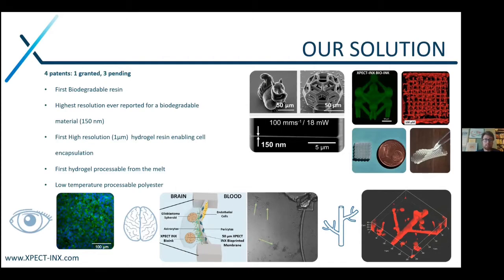We also have a high-resolution hydrogel, which was the first hydrogel enabling cell encapsulation at high-resolution 3D printing. We have the first hydrogel which can be processed from the melt, thereby taking advantage of conventional 3D printing approaches. And we also have a low temperature processable polyester, which can be printed at more cell-friendly temperatures. So these are basically our assets from a material point of view. But then we also have some proof of concept, as we managed to use these materials for corneal tissue engineering, development of a blood-brain barrier on a chip, and also to mimic microvasculature.